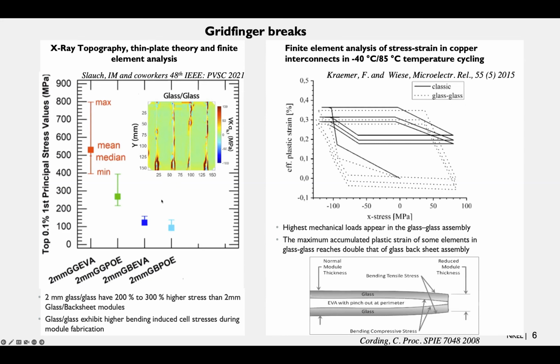Also, we have to consider that glass modules, if there's any of what we call pinching here, lead to some additional stress, which could further exacerbate things like what we see, grid finger breakage at the edges of the cells at the edges of the modules. So in summary of this little section, the glass modules show higher stresses in silicon and interconnects than glass backsheet modules, and we found 3 times the grid finger breaks in the glass modules.